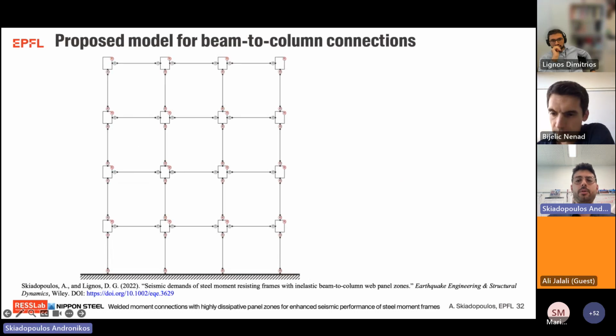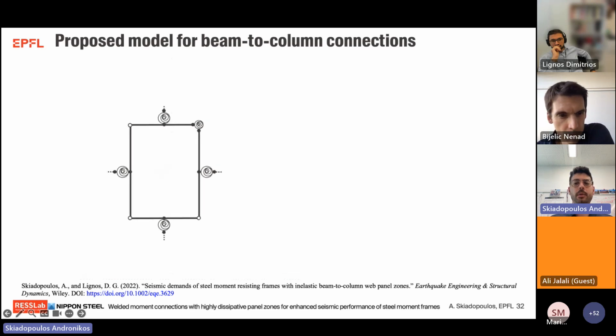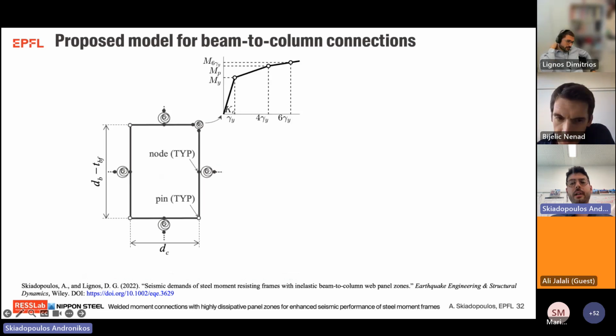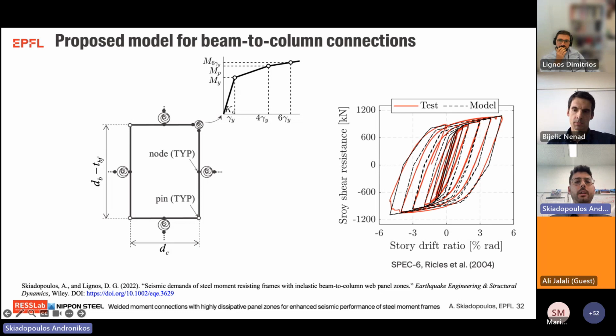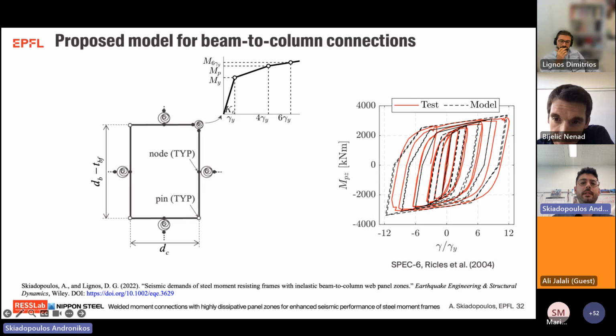To model the panel zone shear response, we utilized a typical parallelogram modeling approach proposed by Gupta and Professor Krawinkler. However, the panel zone hysteretic response is represented by our recently proposed panel zone model that I described before, since this is valid for highly inelastic panel zones and also for column sections with thick flanges. Referring to the beams and the columns, the modified Ibarra-Medina-Krawinkler model proposed by Professor Lignos was employed. And what we observe here on the right side is that the global response of the connection is predicted accurately utilizing this modeling approach. And the same is also evident for the local panel zone response.